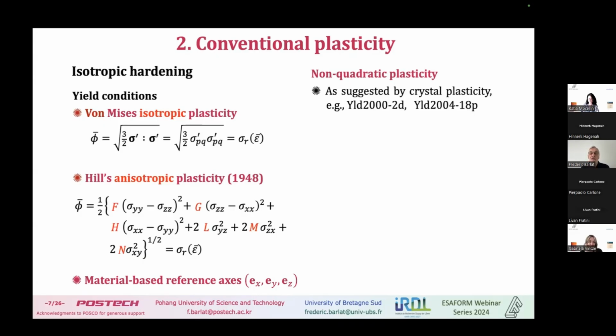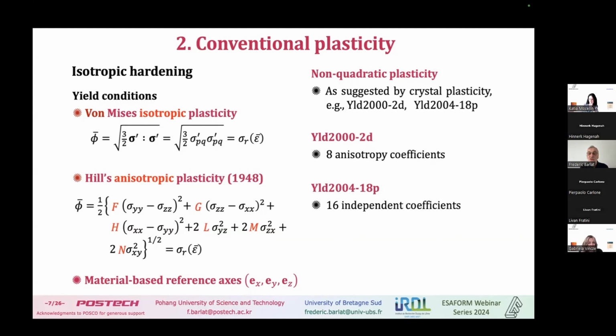Okay, but non-quadratic plasticity models were suggested by crystal plasticity. And so this is the reason new, which they are not new anymore, non-quadratic models were developed. And of course, there are many others after that, but many of them are based on this one or using the same method as this one. So on the two I mentioned, there is a plane stress yield condition or effective stress with 8 anisotropic coefficients. And there's a 3D model which has 16 independent coefficients. Actually there are 18 coefficients, but 16 only are independent.